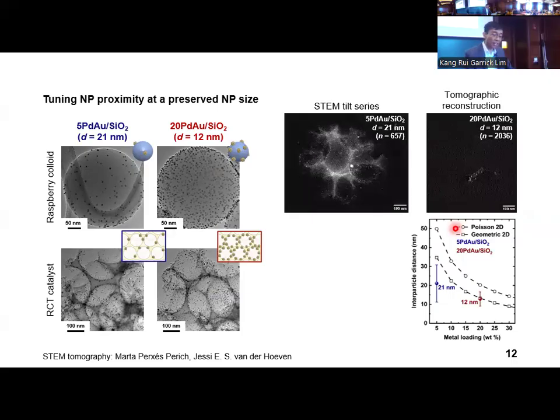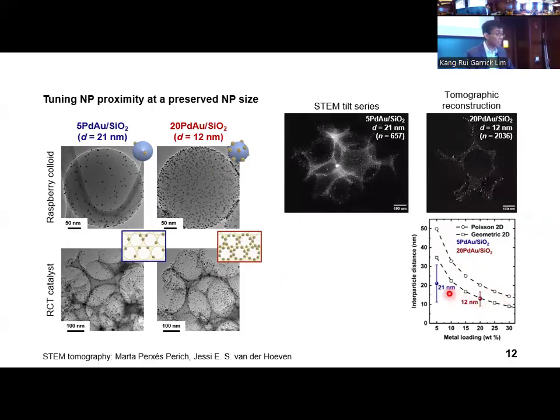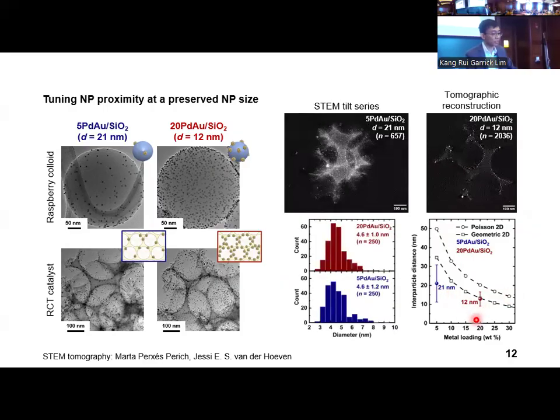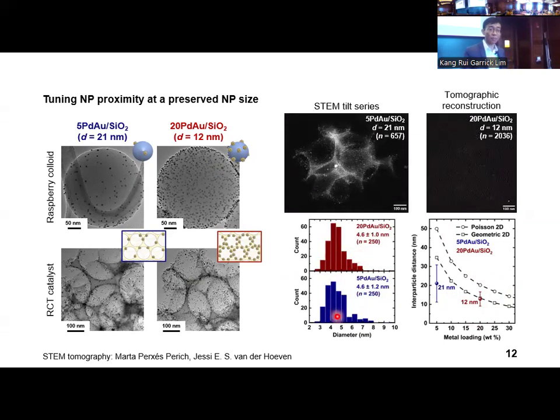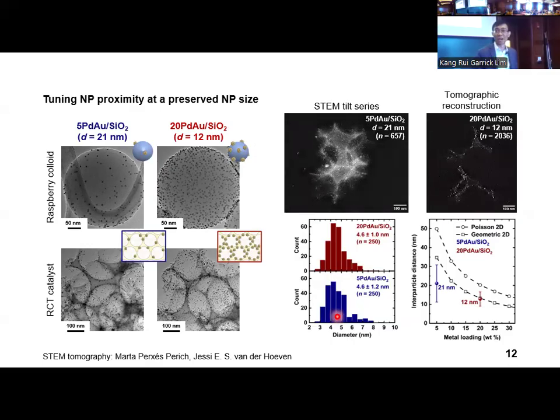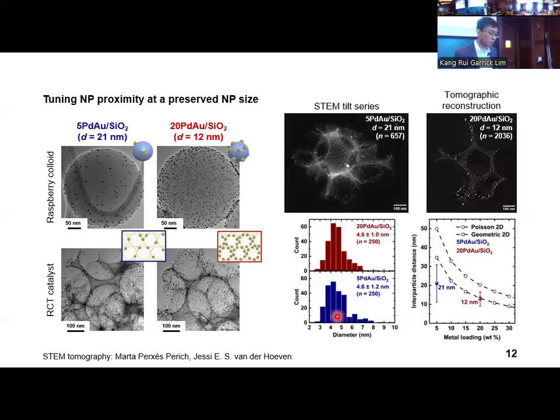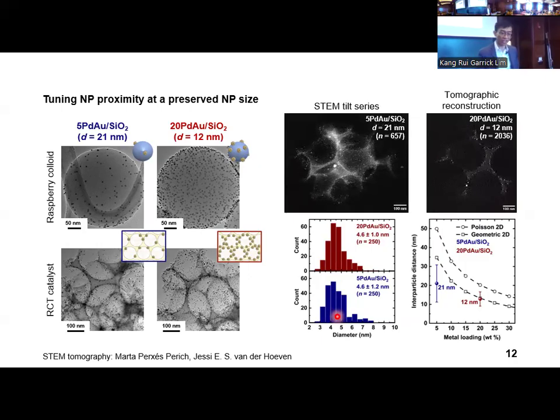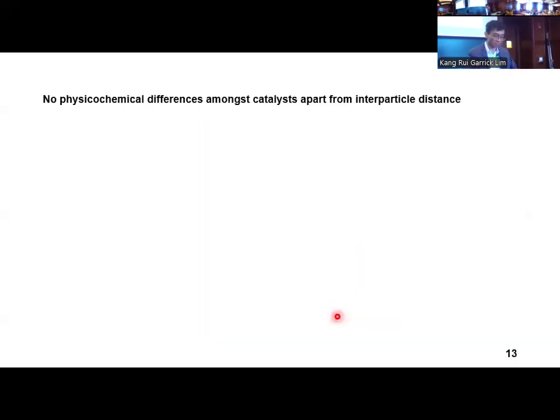On average, the interparticle distance decreases from 21 nanometers to 12 nanometers as the metal loading was increased from 5 to 20%, in line with either a geometric model or a statistical prediction. Importantly, this interparticle distance was tuned at a preserved nanoparticle size distribution, which indicated that we successfully decoupled nanoparticle proximity from nanoparticle size. This deconvolution cannot be achieved using existing catalyst preparative methods.